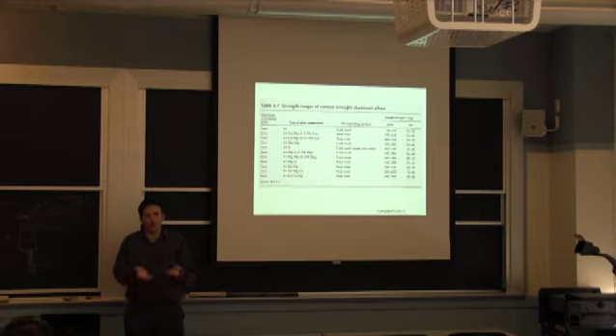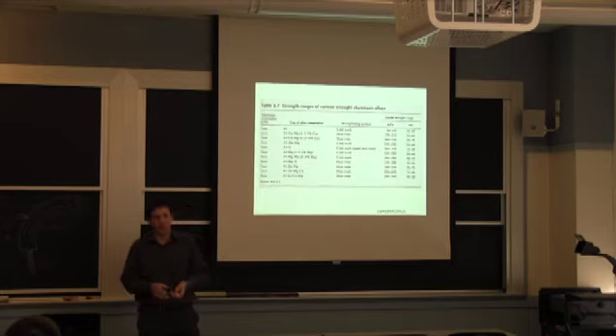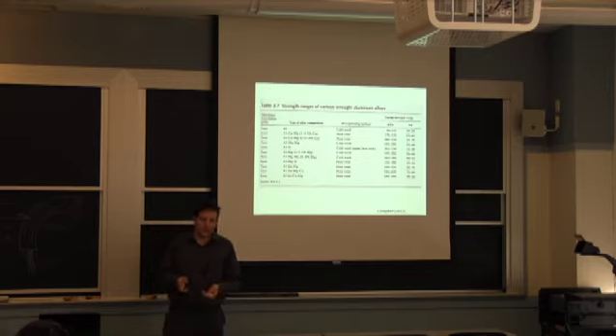And then you go through one more step that we call aging, where you heat it back up just a little bit. It's not a very high temperature, and you help the formation of very fine precipitates, or a dispersion of precipitate, that's going to increase your strength. It's like making very strong barriers against the dislocation in the material. It's a different process than everything we talked about for steel. For steel, we were talking about all the carbon and everything just sort of staying in solution, and then we have this martensitic transformation, whereas here, when you cool it down, nothing happens.